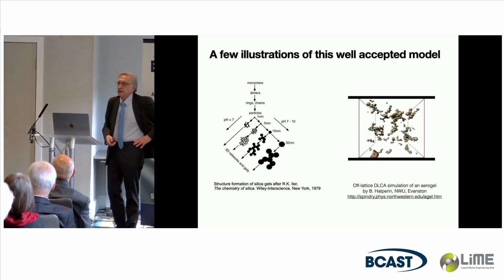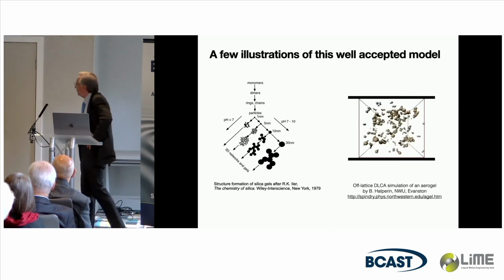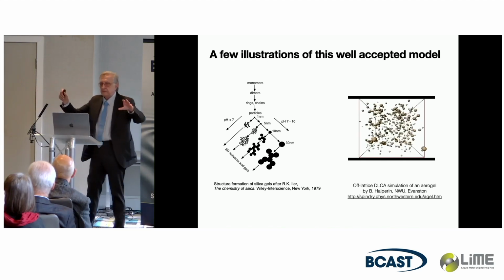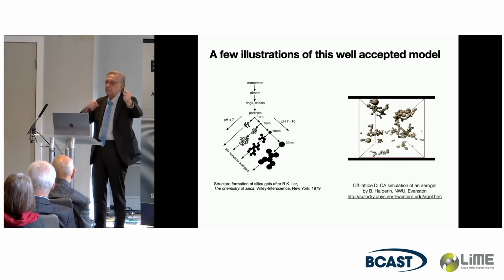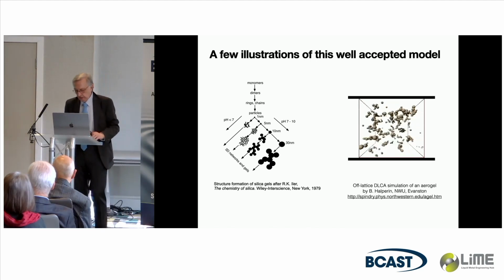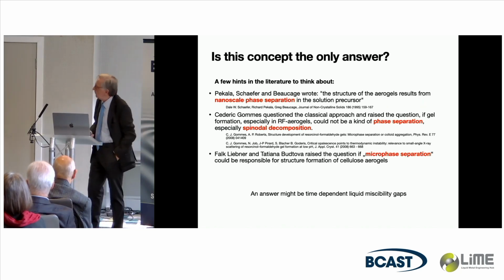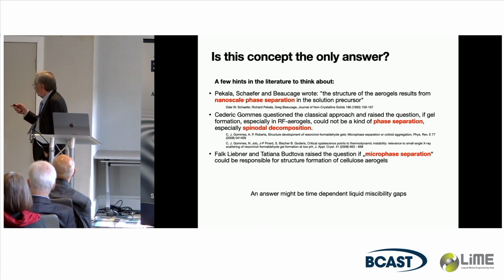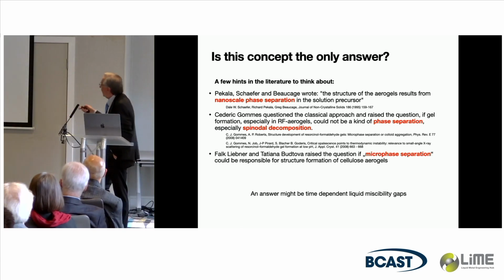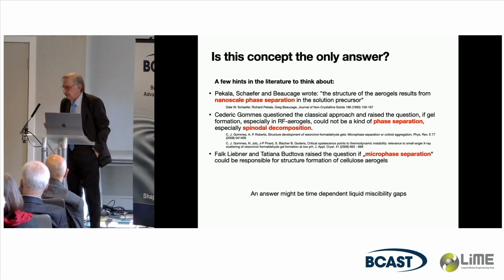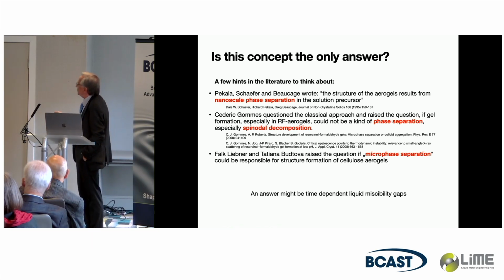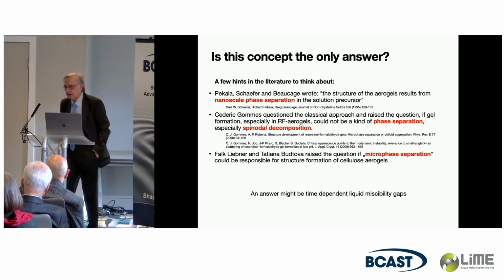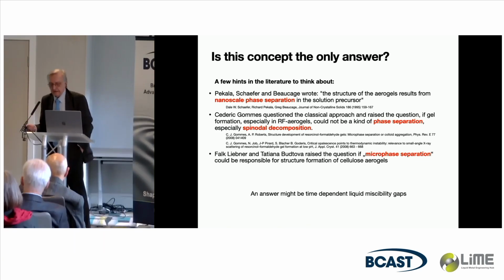Here's a wonderful DLCA simulation done by Bill Halperin from Northwestern University with different particle sizes. Depending on the mass, they make Brownian motion, and they made at the end a spanning cluster. Wonderful. But going back to the mid-90s, there was still the idea that maybe this cluster aggregation, this Brownian motion, is completely nonsense. Maybe it's phase separation. Cedric Gommes from Liège looked into that and said it's either a kind of phase separation or spinodal decomposition. It's difficult to discriminate from, let's say, small angle X-ray scattering.